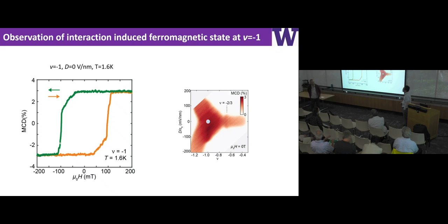Maybe I can comment on your question. One difference between gallium arsenide and your platform is that you have a dispersion in your bands. It's not large, but you have a dispersion. So you are allowed to get a Fermi liquid, which you couldn't get in a Landau level, and that competes with your fractional states. Presumably between -1 and -2/3, as you also suspect, the fractional states lose the competition and you get the metal instead. So there's a phase transition into something, then it comes back to the topological state.